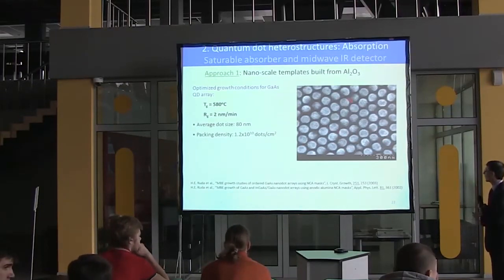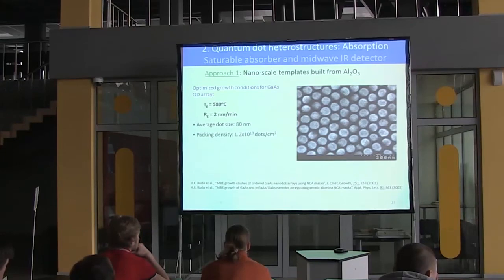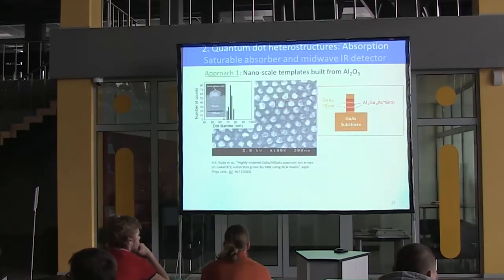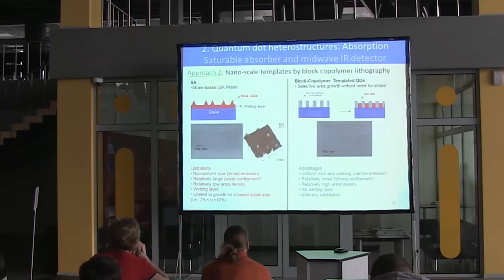And you can see they're very close to each other. They form a hexagonal lattice, right? I can control their size and whatever. That's one idea. Or I can get really clever. Not clever, but I can get really ambitious. And here I've put 2 quantum wells, actually, in the quantum dot. So I have disks of confinement here and here, because there's gallium arsenide in between aluminium arsenide twice in the dot, right? And that's what each of these dots are. So you can make very complex heterostructures in that way. I'll come back to why that's kind of interesting in a little bit. But actually you'll see pretty well now.